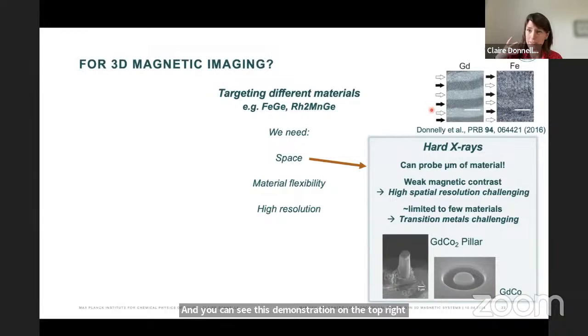This is the same sample. It's an iron gadolinium multilayer. When we look at the gadolinium edge and the iron edge with roughly the same statistics, we can clearly see what's going on in the gadolinium, but the iron is much, much more challenging to resolve experimentally.